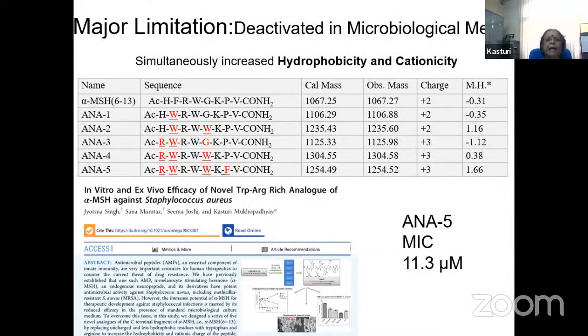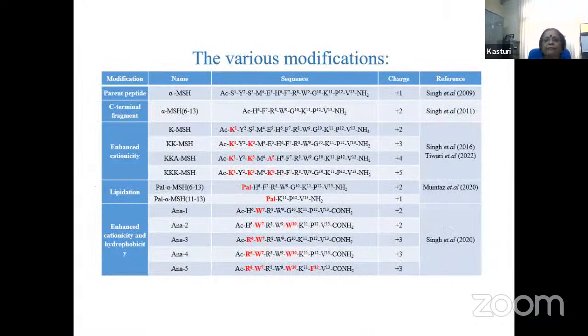So what we did: we tried to develop a different kind of peptide, because the major limitation of these alpha-MSH based peptides is that they are inhibited by biological media. So we tried to rectify that by introducing hydrophobicity, like arginine and tryptophan. And then for the first time we could manage to measure the MIC, because the MIC experiment needs microbiological media. This paper has been published in Scientific Reports. And then we have done a lot of